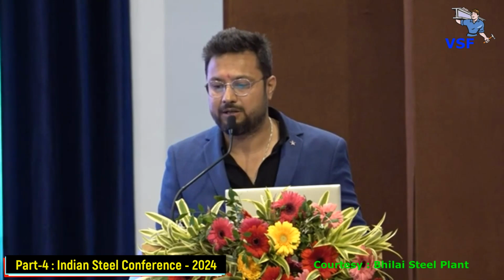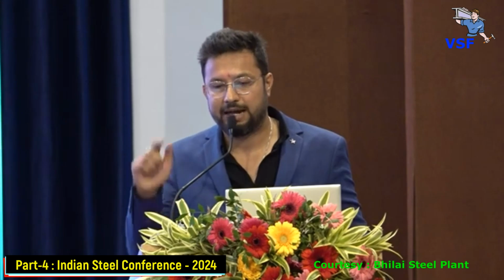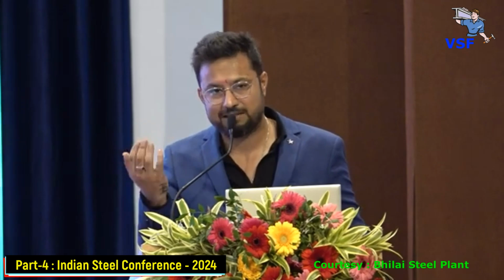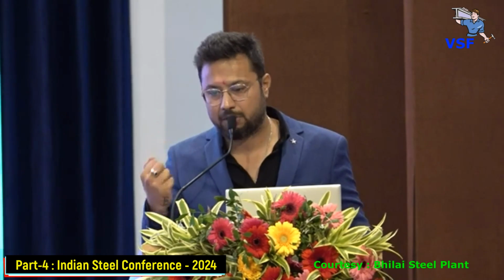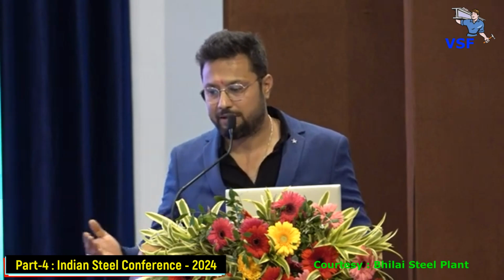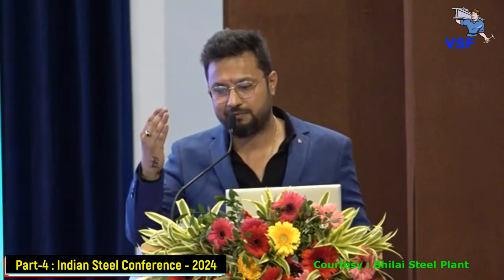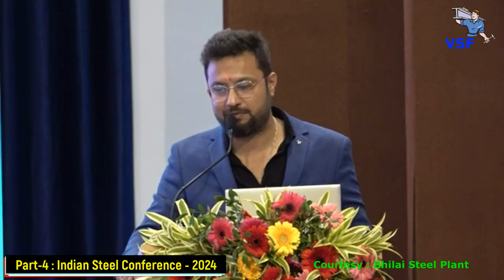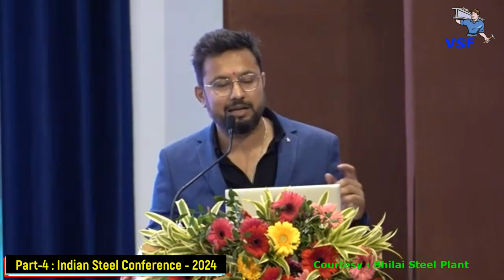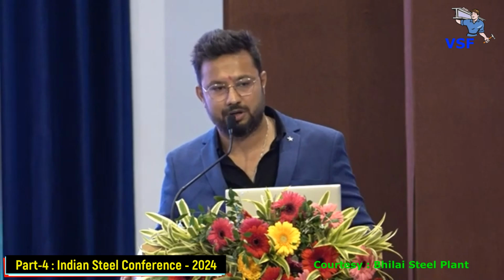So, if we compare the RS2 system with the spray technology, we see that not only on the head, which has the prime impact of the wear, but also all throughout the length, from 2 mm from the surface till 40 mm from the surface, we have a consistent value of hardness, which is a key requirement when we talk about the new generation of rails.